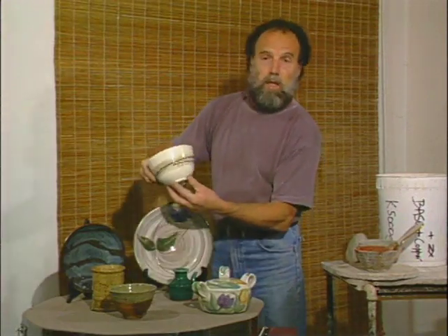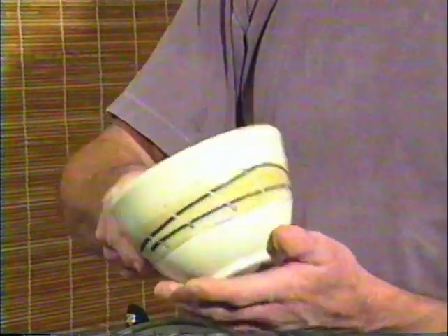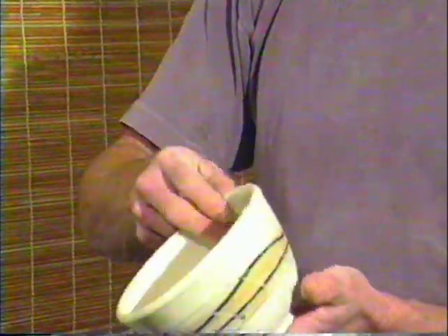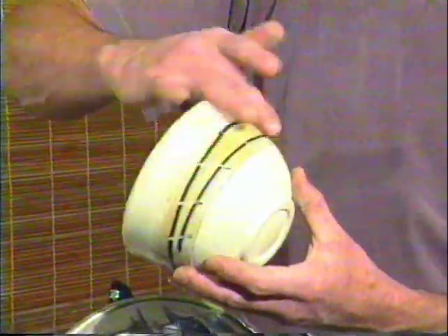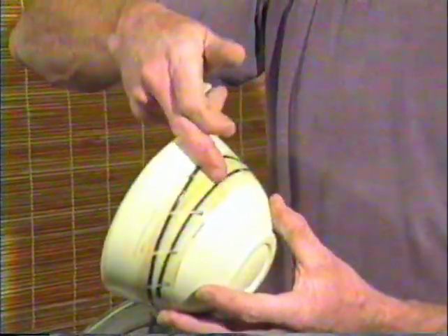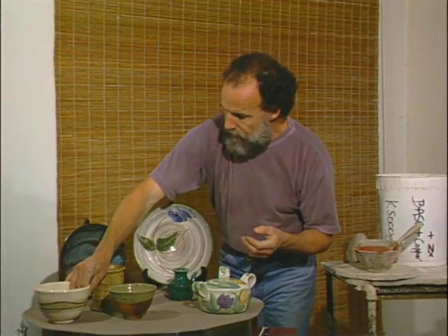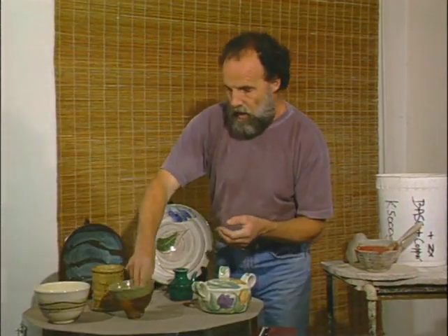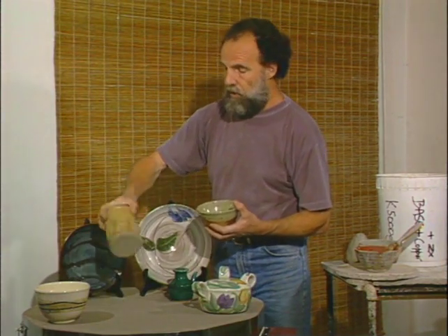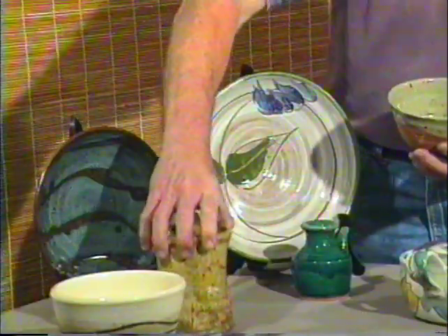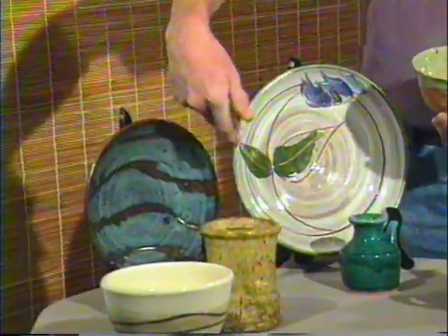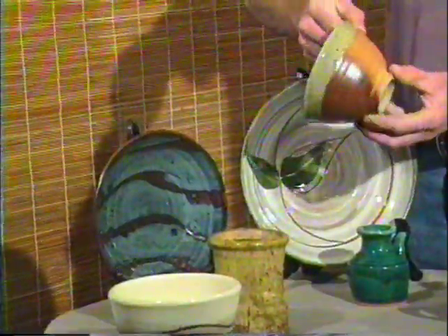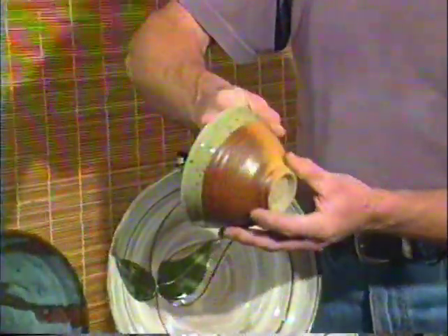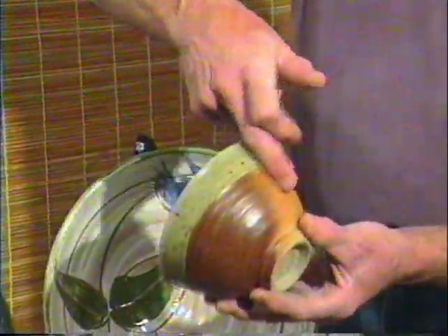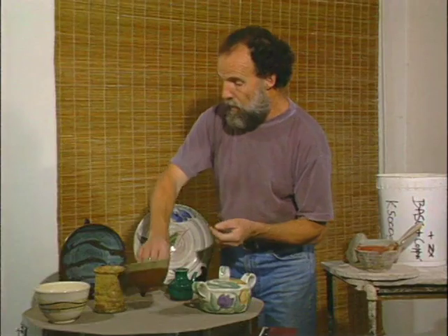This piece here by Gabriola Island potter Ron Holmes is an example of mid-fired ware. This particular piece is fired to a nice maturity at cone 6 and has a similar use to the piece I just showed you of slips under a clear glaze. And lastly, these pieces here, which are mine, are fired at high fire reduction. We have here an ash glaze pot. This pot here was fired in one glaze with another one over the top of it, and this particular piece has been wood fired to cone 10, and you can see that the effect of the wood is quite strong on the exposed clay body there.